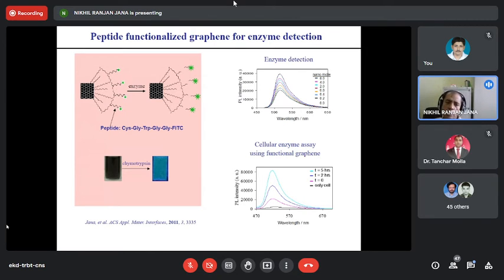So graphene, you heard about this. This is a functional graphene. Colloidal graphene linked with a peptide, linked with an organic fluorescent dye via a peptide-based linkage. This peptide can be cleaved by the enzyme chymotrypsin. Because this organic dye is very near to the graphene, and graphene can quench the fluorescence of this dye, the fluorescence is off. Once the enzyme is present, the enzyme can cleave this peptide bond. The organic dye is away from the graphene, and this will lead to fluorescence switching on. So the enzyme can be detected.